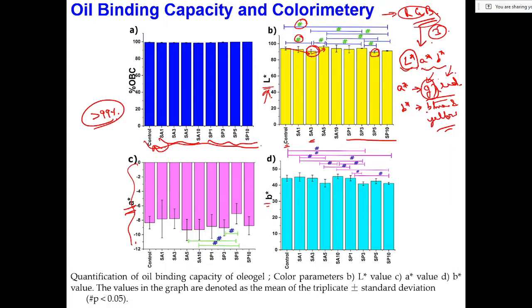Okay. Similarly, when we looked into the B star values, the negative values show the blue component, whereas positive values show the yellow component, and herein we were able to see the yellowish component. Okay. Now the thing over here is that you would say, sir, in the images we could not see any green component. Why didn't we see it? If you compare, the A star values are all limited within a range of 0 to -10. Whereas the B star components, if you see, are much higher than the A star components. So we can say that the yellow component has a large proportion in the sample as compared to the A star values.